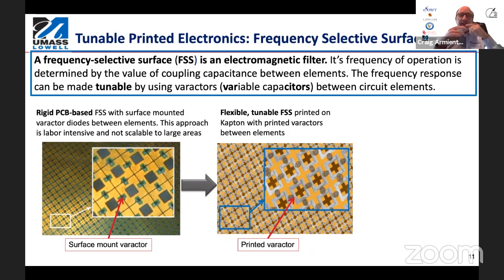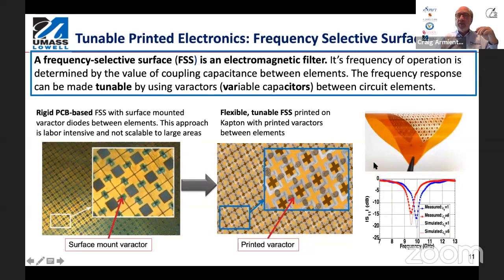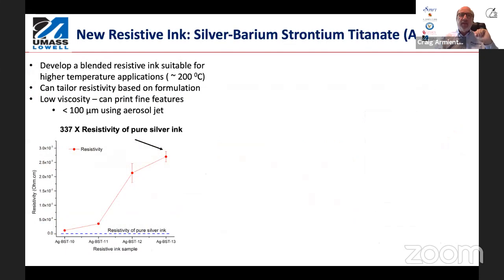What we've done is taken the extra step and connected these unit cells with an interdigitated capacitor, which has our tunable dielectric material as the dielectric. And as a result of that, you can see in this photograph here, we have a flexible and tunable FSS structure, whereby changing the voltage across, we can tune the frequency response of this FSS. So again, this is a novel material enabling tunability that's not available commercially.